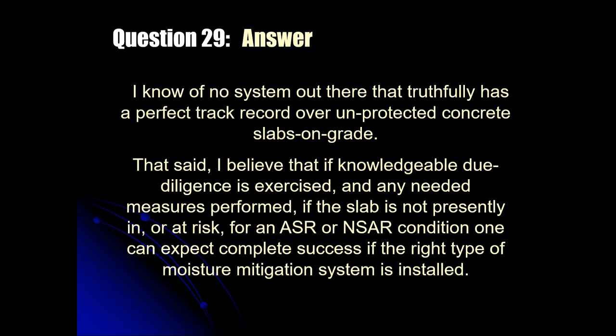That said, what we've learned from the failures that we've investigated over the past number of years is that there are ways to achieve a very high degree of potential success, but it involves a due diligence process that is not necessarily being followed as often as it should be. There are things we need to know about the concrete. We need to know about the components in that concrete mixture. We need to know about the variation in salts content from the very surface of the slab to the body of the slab. We need to know if there are potentially reactive aggregate particles in that concrete. But once we know all this, I do believe that we can successfully install a moisture mitigation system with a very, very high potential degree of success.